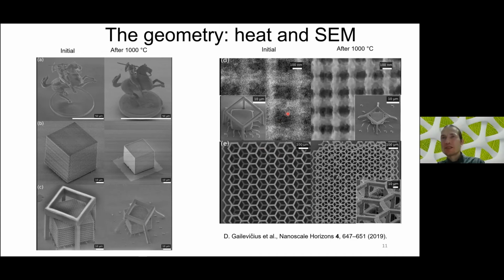Some extreme examples of initial structure and after 1000 degrees, so we can see that you can go down to 100 nanometers or slightly below. This initial blurry structure is because we could not gold sputter and heat then, yes, so we just image it without gold sputtering for conductivity needed for SEM, and this one is more clear, but it's the same structure.